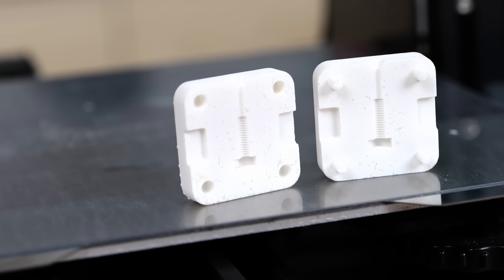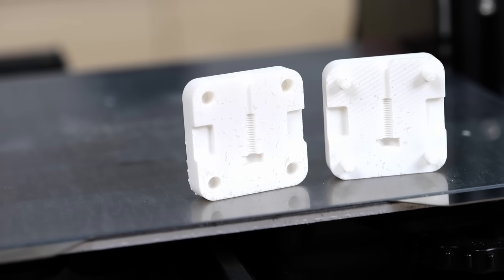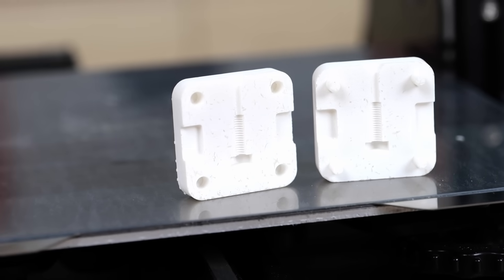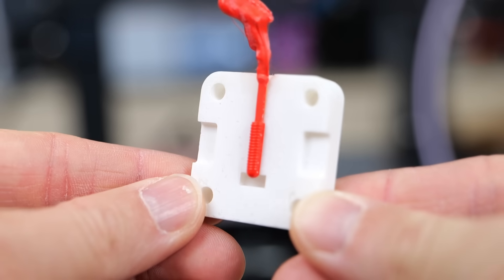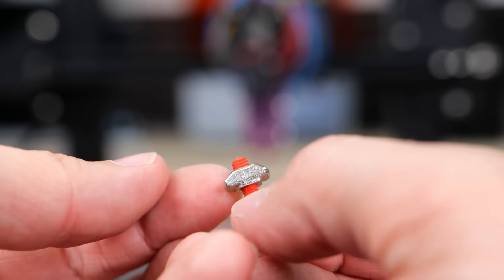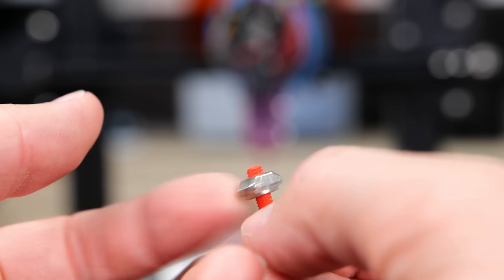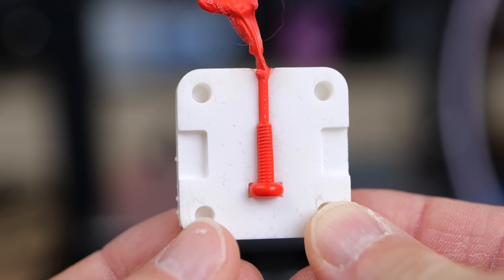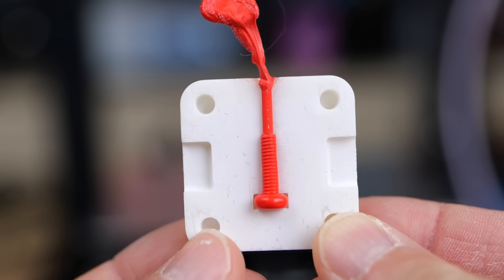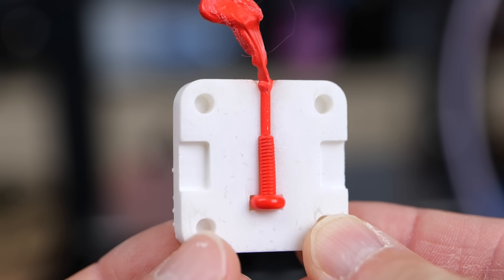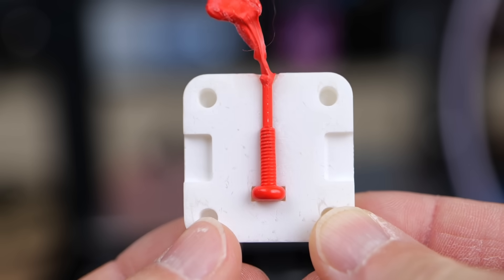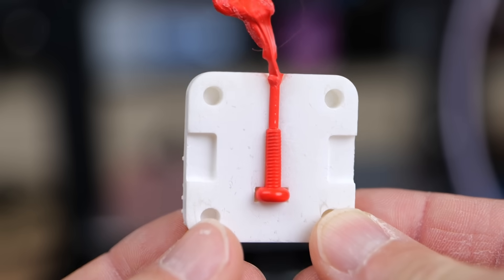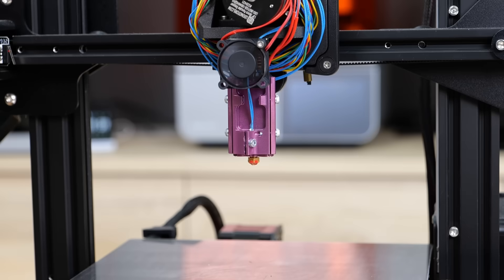Because I was curious I switched back to PLA and tried this simple mold of an M4 screw that I made, but it had severe problems filling this one again. I played a bit around with the parameters and got a working screw out of the mold yet never managed to fill the hex. Maybe the injection pressure of a 3D printer is here the limiting factor or our 3D printing material grades are not suitable for injection molding. At this point I also stopped working on the project for now.